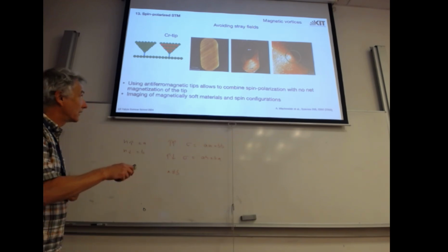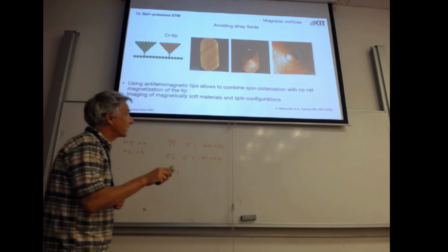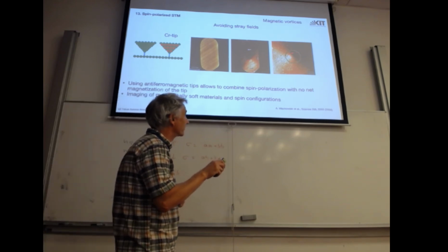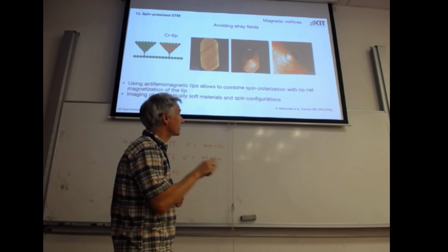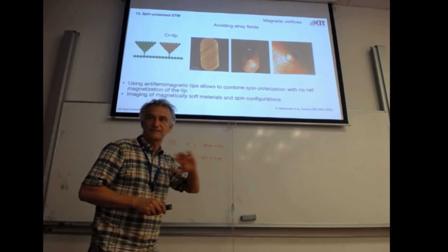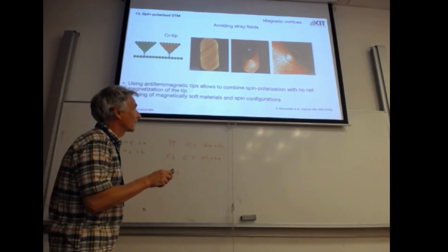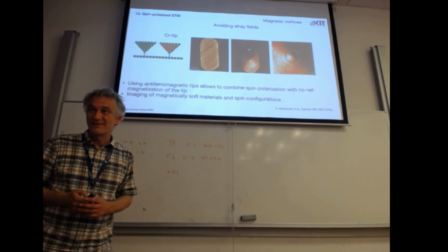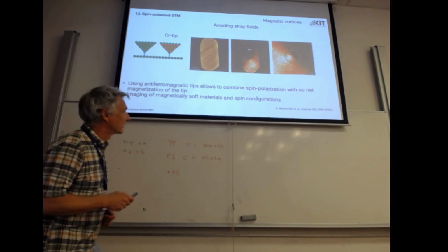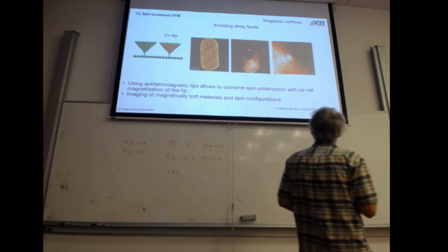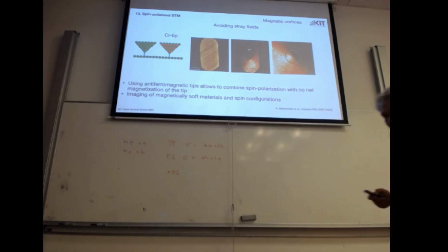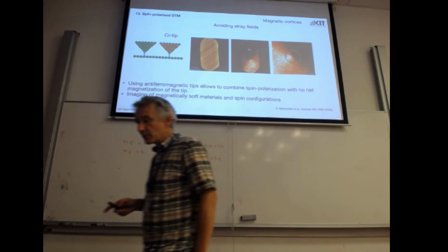Okay, so this is an antiferromagnet, so you can actually measure the center of this vortex core pretty precisely. If you would try to do that with a ferromagnet, the stray field would move this object. The scale bar there is 10 nanometers. So it's very good resolution. Oh, it's atomic, I will show you.